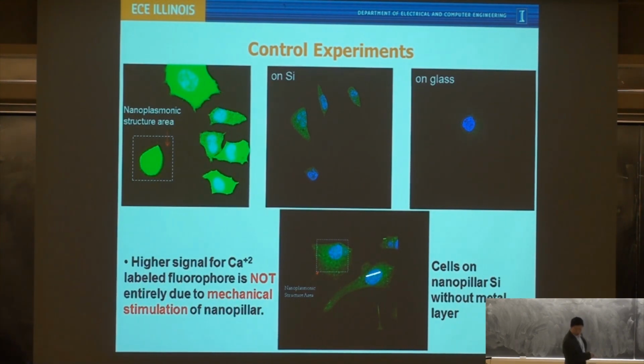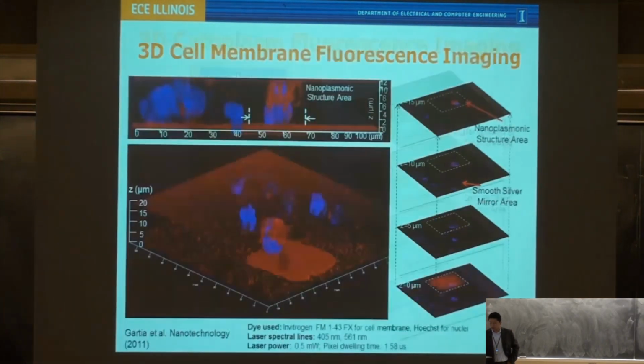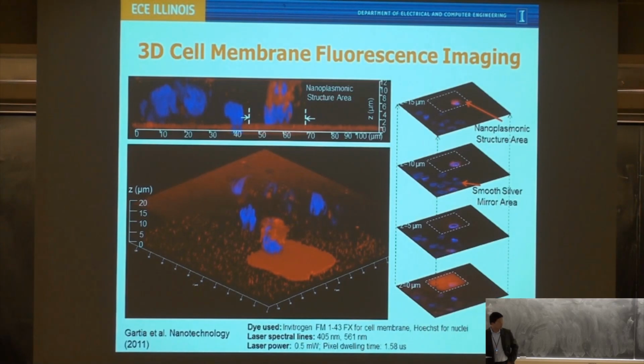This is showing that without metal layers, there's almost no difference between the intensity of the cell inside and outside. So we did some control experiments to prove that we did have very significant enhancement when the cell is sitting on top of nanostructures, for both membrane and cytosol, but more on the membrane.